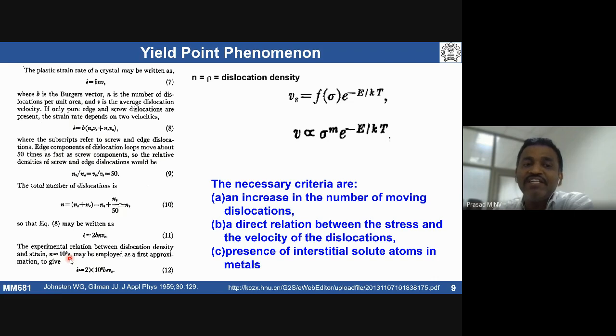What does it mean? With increasing strain, the dislocation density is going to increase. However, according to this equation, even if you increase strain by just 1% or 0.1%, the amount of dislocation density initially is very high.